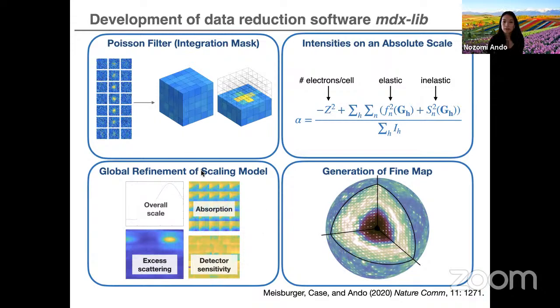Another really important innovation was to put intensities on an absolute scale of intensity of electrons. There was a really neat trick involved in this, but the reason why this was important was because this allowed two things. One was we were able to subtract the inelastic contribution, which has no structural information. It's only the elastic scattering that tells us about how scattering from different atoms will interfere to form the pattern.